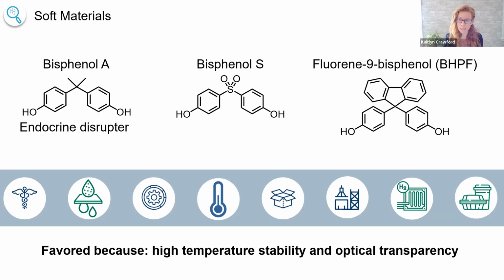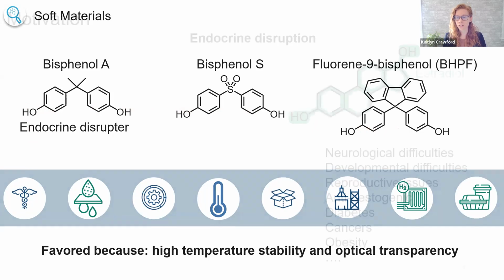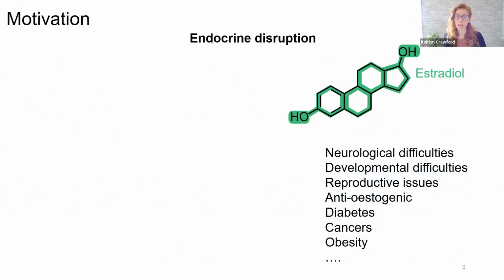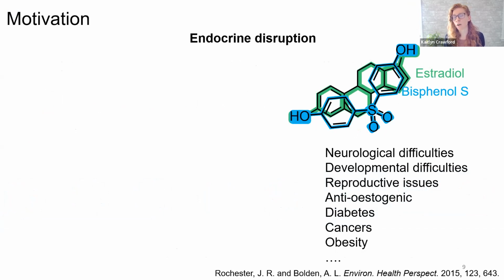The reason I want to focus on these is because if you notice the location of these hydroxyl groups, these are the OH bonds here and here, that for the bisphenol S and the BHPF, they're in a similar location. So when we take a closer look at estradiol, which is the estrogen hormone where BPA fits in, you see that the overlap with the OH groups is really close. And this is one of the reasons why the BPA and also BPS and BHPF are actually endocrine disruptors. So these will cause things like neurological difficulties, developmental difficulties, reproductive issues, diabetes, cancers, obesity, and the list is even longer than that.